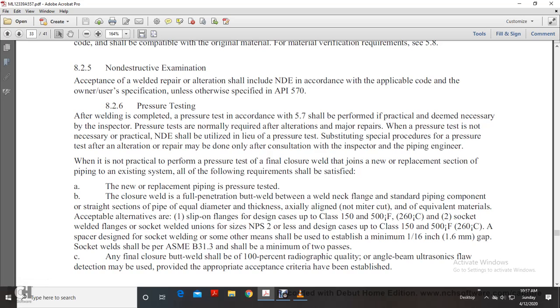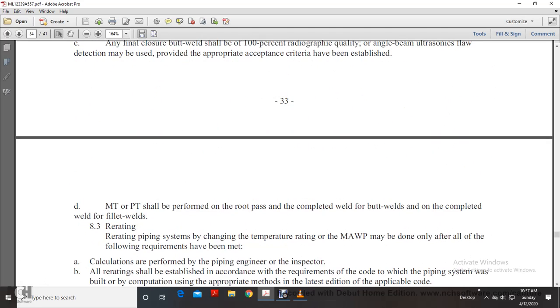Spacer designed for socket welding, or other means that should be within established 1/16 of an inch gap. Socket welds shall be per ASME B31.3 with a minimum of 2 passes. Any final closure butt weld should be 100% radiographic quality, angle beam ultrasonic flaw detection may be used to provide appropriate acceptance criteria that has been established.